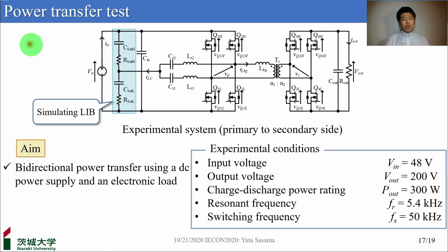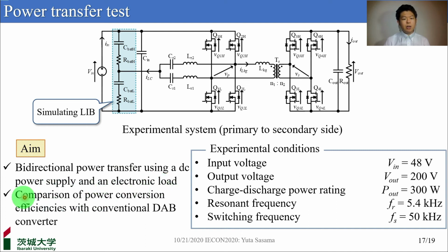Now, I'd like to show you a power transfer test. In this test, we simulated the lithium-ion battery using large-capacity electrolytic capacitors and bidirectionally transferred the power using the DC power supply and the electronic load to investigate the impact of resonant tanks. Power conversion efficiencies of the DAB converter alone were also measured by removing resonant tanks. Here are the experimental conditions. We set the switching frequency to 50 kHz so that it is far from the resonant frequency.